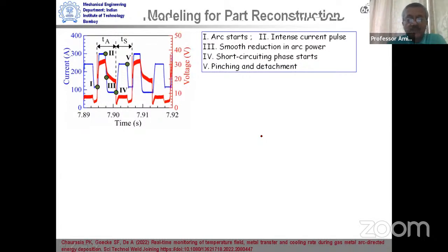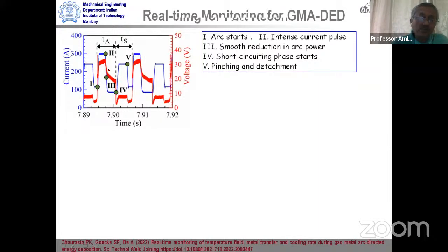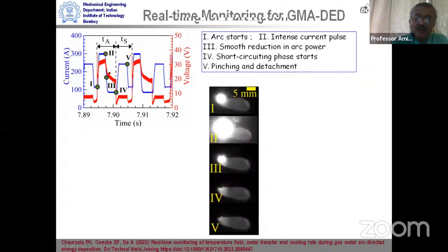So if we talk of monitoring, what can we do for monitoring? For a typical GMA process that we use for this kind of directed energy deposition process, this is a typical current and voltage cycle, very complicated cycles, so that the heat input can remain as small as possible. Now, one way to monitor the process is to see how the arc is happening. We should not allow the arc to grow much bigger. So if we look at different steps throughout one cycle, we see that it goes from a small to a large arc, melting, then immediately it's again a smaller arc, and this is a typical melt pool. This is the typical melt pool we are looking at longitudinally as the deposition is going on.